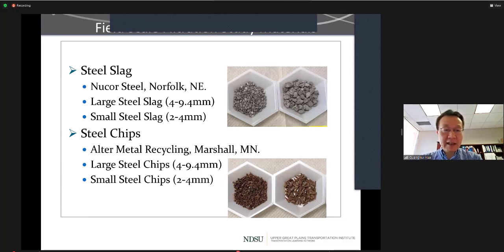And we collected steel slag from Nucor Steel, Norfolk, Nebraska. And we processed the material into two sizes, a large and a small, which are 4 to 9.4 millimeters and 2 to 4 millimeters respectively. And for steel chips, we collected from a recycling company in Marshall, Minnesota. And also we processed the material to the same size range as the steel slag.